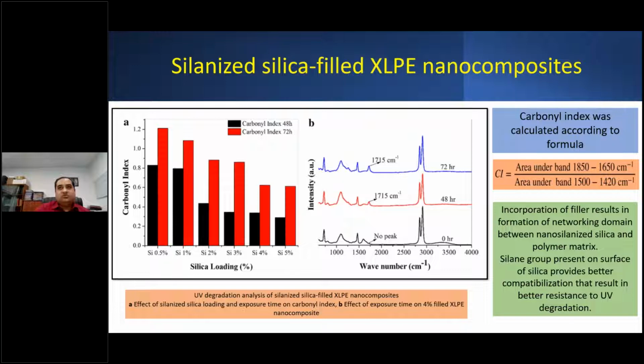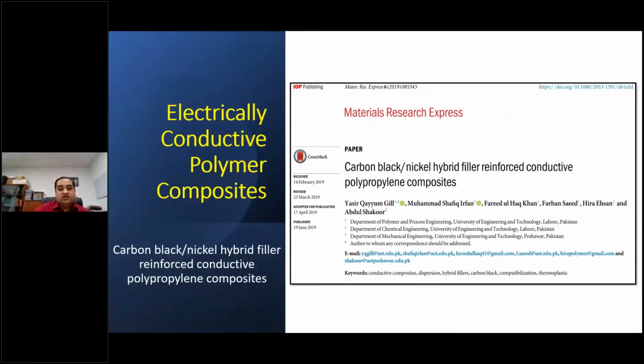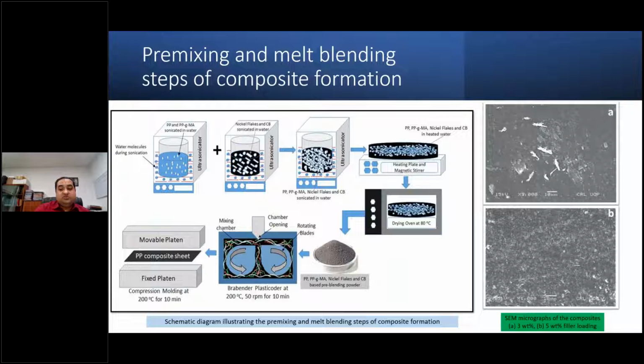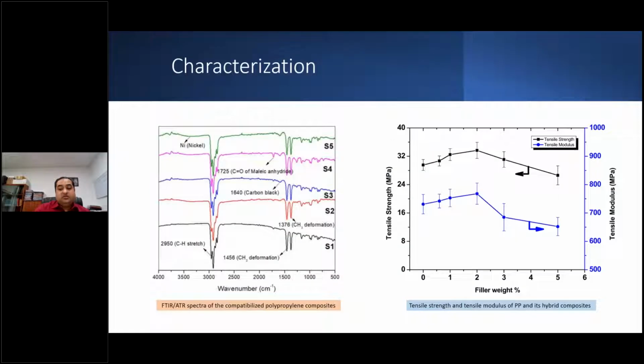So in this research, we were also able to develop, first of all, a processing technique that is overall economic in nature and can give you enhanced properties with very little formation of agglomerates at very high weight fraction. FTIR and tensile strength measurements were carried out, and they showed improvement of properties at 2 weight percentage of filler addition, and later on a decline in the properties was experienced.